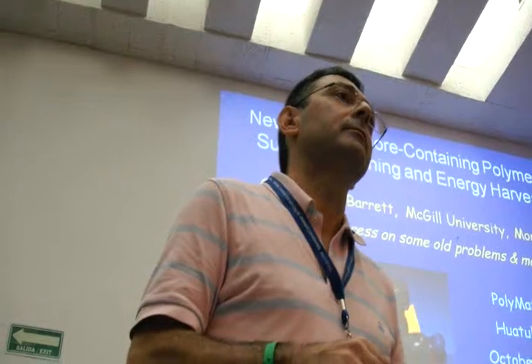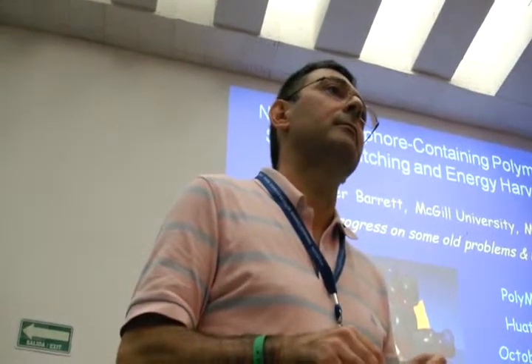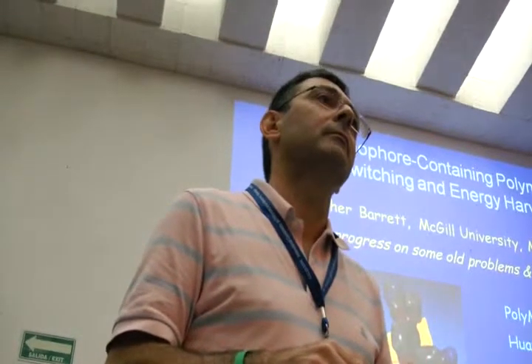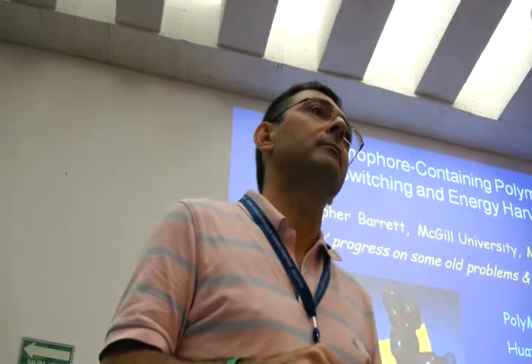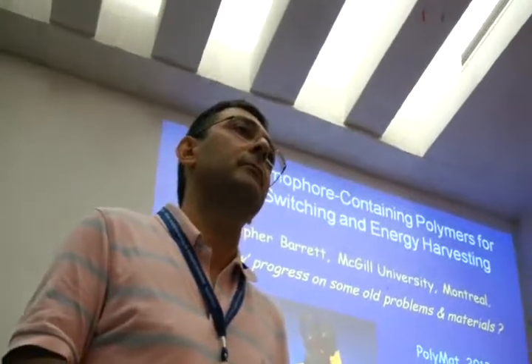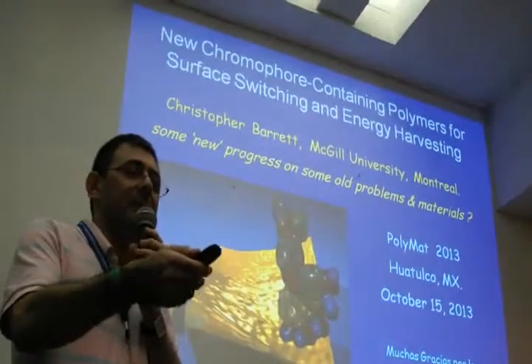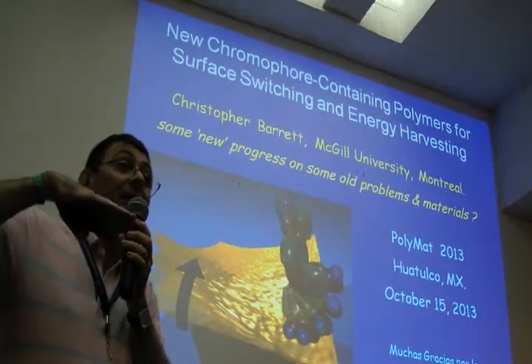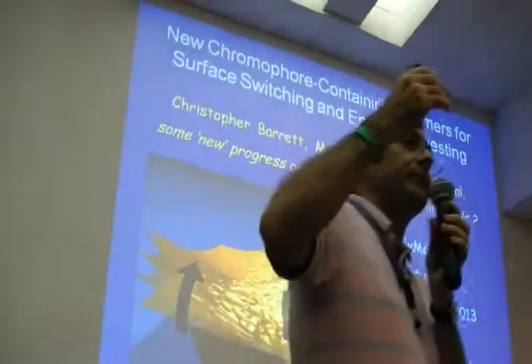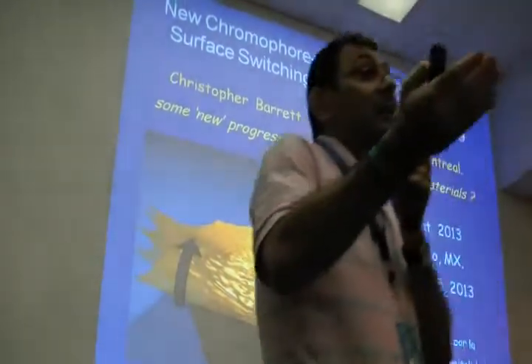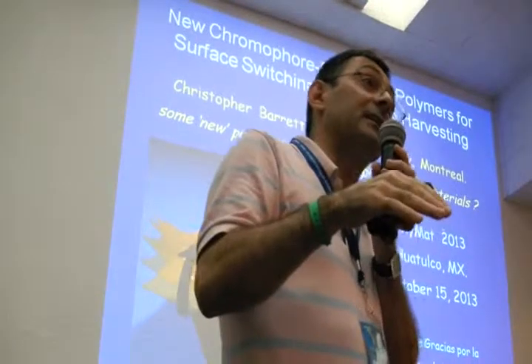So the diacrylate that you use as a cross-linking agent is also the best compound to exfoliate graphene. At present. So now, if you use it in the presence of another monomer, could the diacrylate partition around graphene so that the concentration or the density of cross-linking points is higher close to graphene, and the more graphene you have, the less cross-linking agent you have in the polymer section, which will give you a decrease in the modulus? Yes, I think it's something similar to what happened as well in swelling behavior, because you have a decrease in the cross-linking degree, and so probably you will also see a decrease in the properties, if I understood exactly what you were saying. But the cross-linking agent